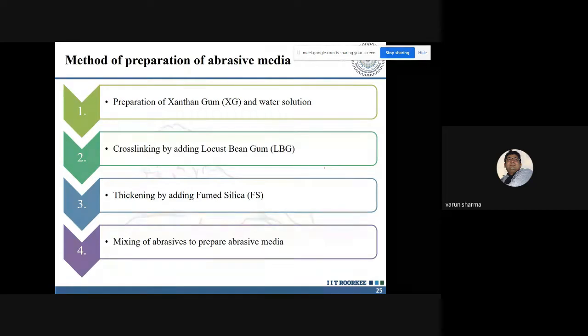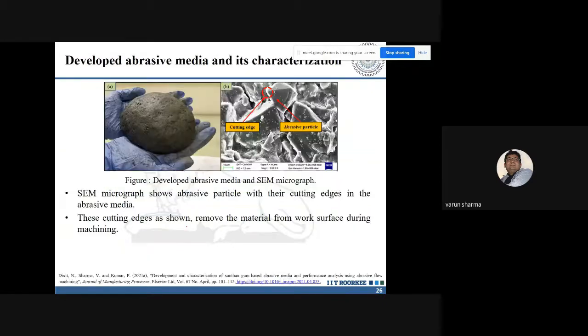So for the media development, we used xanthan gum. It is biodegradable, biocompatible, and has good strength. Now, to make sure that this xanthan gum cross-links nicely, we used a cross-linking agent, locust bean gum. It did not have the desired viscosity to hold the abrasive particles. So we used fumed silica to give it the desired thickness, and then we mixed the abrasive particles into that fabricated abrasive media. Now this was the media that you can see that was developed in-house.